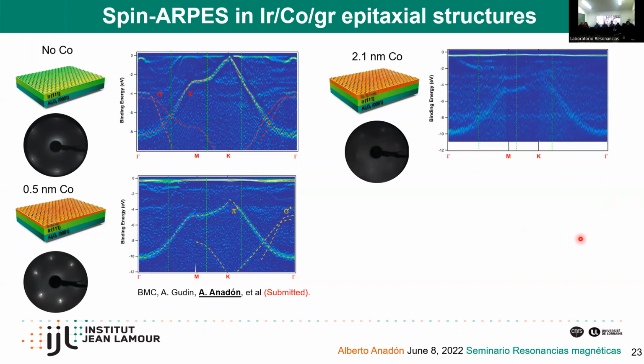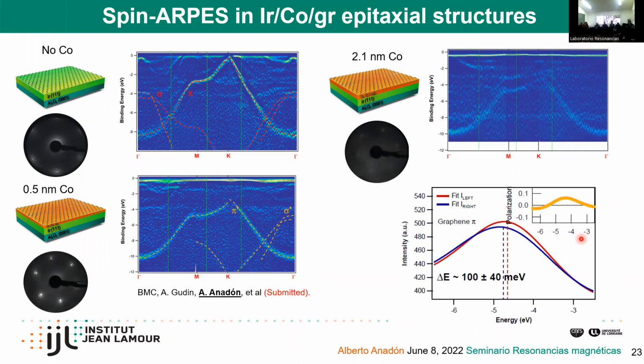We can also see how the spin splitting is in the bands. And basically we find that we have a significant spin splitting. This is in the same order of magnitude as some first principle calculations that we have done in a graphene cobalt with 3 monolayers system. So if you are interested in this, you can have a look at our recent papers. This is still unpublished, but all the calculations are already published. You can look for them.